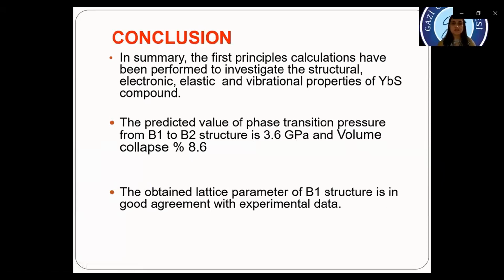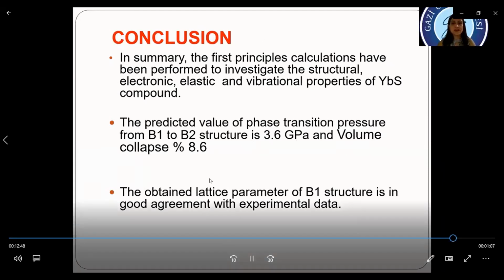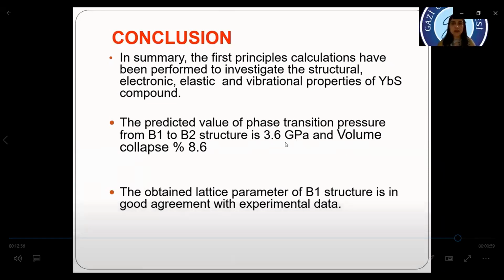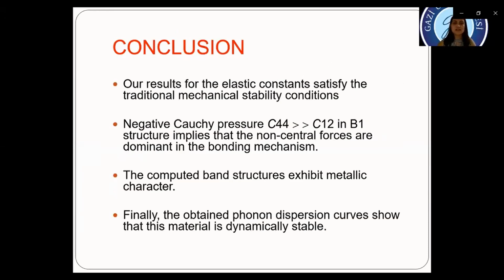In summary, first principle calculations have been performed to investigate the structural, electronic, elastic, and vibrational properties of the ytterbium sulfide compound. The predicted value of phase transition pressure from B1 to B2 structure is 3.6 gigapascal, with a volume collapse of 8.6%. The obtained lattice parameter of the B1 structure is in good agreement with experimental data. Our results for the elastic constants satisfy the traditional mechanical stability condition. Negative Cauchy pressure in the B1 structure implies that non-central forces are dominant in the bonding mechanism.